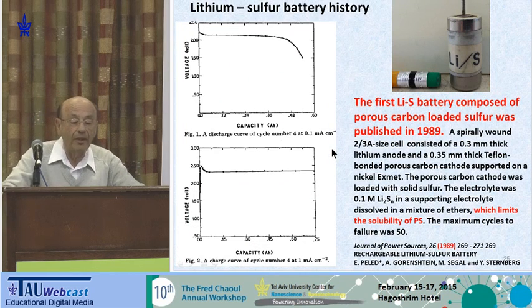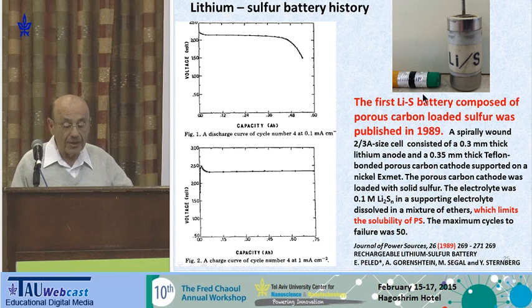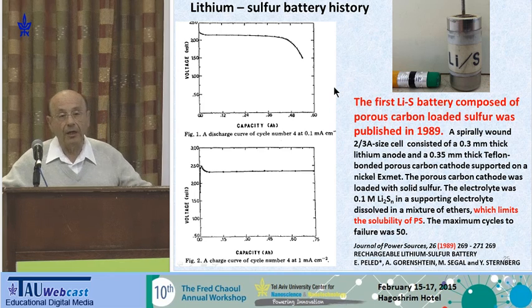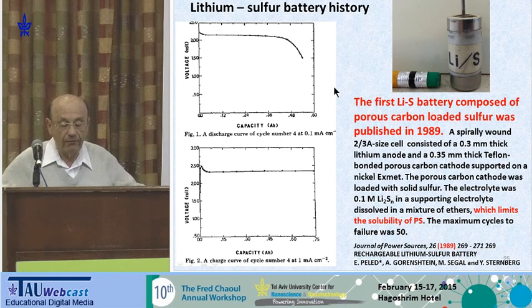Next issue is the lithium sulfur battery, and a piece of history. The first lithium sulfur battery that was assembled with porous carbon loaded with sulfur was built in my laboratory and published in 1989. And this is the discharge and charge curve for this cell. We were not able at that time to solve the problems of cycle life, and we got internal shorts and other problems, and so the sulfur was soluble in the electrolyte and attacked the lithium anode, and we stopped it, and we came back to it only 3 years ago when we had new ideas how to solve these problems.